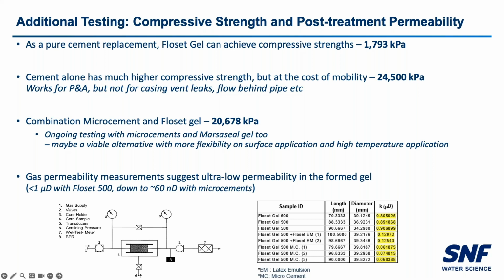In terms of the permeability, we can see whether we're using Floset Gel 500 with and without micro cements. We're into the sub 1 microdarcy permeability, or down into the 60 nanodarcy territory when we have micro cements added. So we feel like that's a pretty good gas permeability to be working off of.